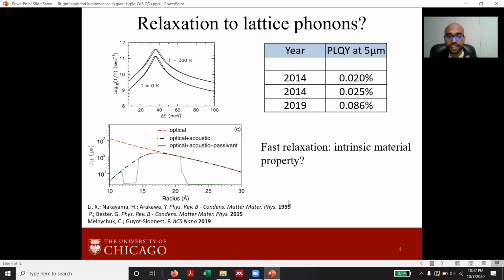In 1999, Arakawa from the University of Tokyo proposed a simple model of coupling between the intraband excitation to lattice phonons. And using a simple two-level Wigner-Weisskopf formalism, they calculated the scaling to be 1 over energy squared trend for the lifetime. If we extrapolate this plot to 5 microns, the lifetime would be of the order of nanoseconds. More recently, in 2015, Han and Bester did a similar calculation using DFT, and they too saw the relaxation between the nanosecond and picosecond timescale.